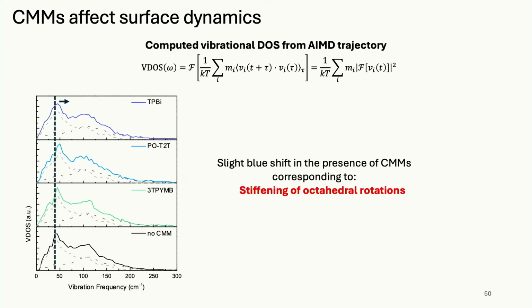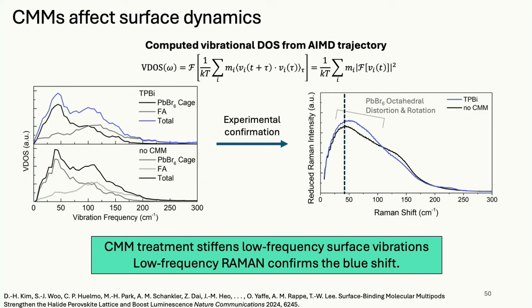And the point is my friend Omer and his group took Raman spectra of these actual materials. And wouldn't you know it, the Raman frequency experimentally does shift upward. So that was a prediction that we made that he was able to show. Here, this is the experiment. This is the one without the stiffener, and then you can see the blue peak, it again shifts. This is actual experimental data.